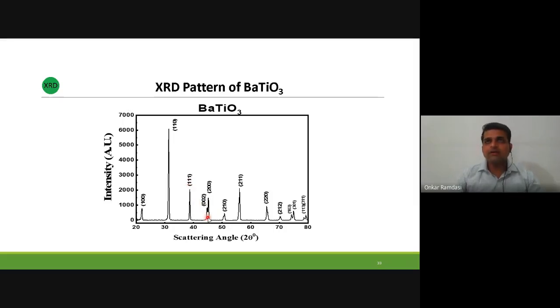So if you take the readings with respect to temperature, let's say this is room temperature, 30 degree, 50 degree, 60 degree, we can see that with increasing temperature, the split peaks will merge into a single peak. So from that also you are able to predict the phase transformation temperature or Curie temperature.